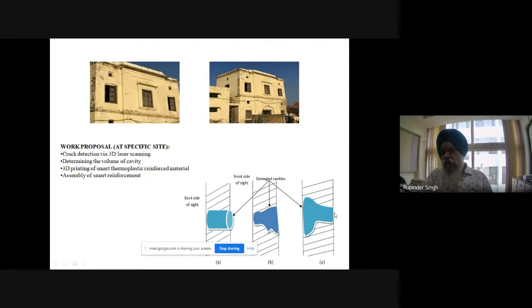Then there is a third condition when the entry is small, but on the rear side, which is not accessible to me, the crack is large, and it may propagate in a big way in the upward direction as well as in the downward direction. Then what will I do for filling this type of crack, and how will I get information on whether the crack has been filled properly? One of the basic things I can do is some scanning. We have an ultrasonic scanner, so we get the geometry of this component. Once I have the geometry, I know the volume of the component, right? I know how much volume of the filler I have to fill into it.